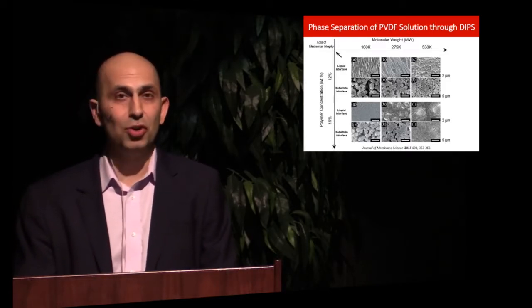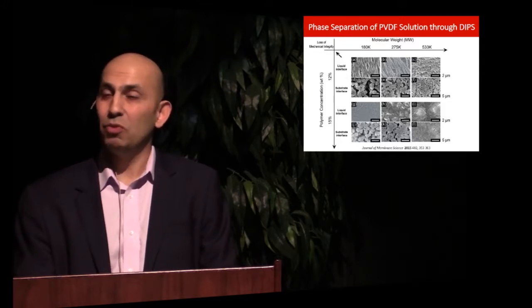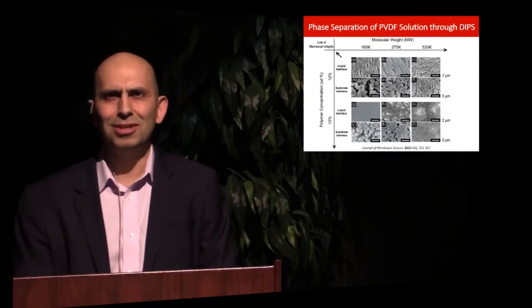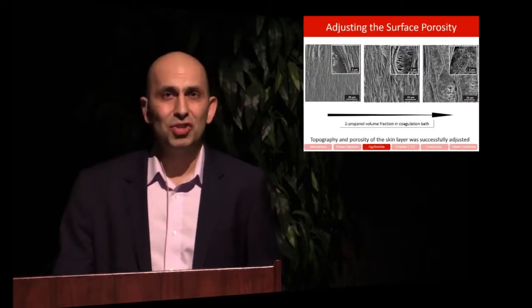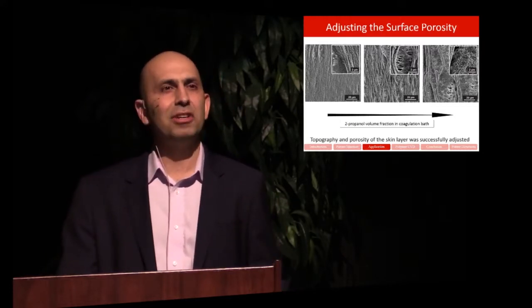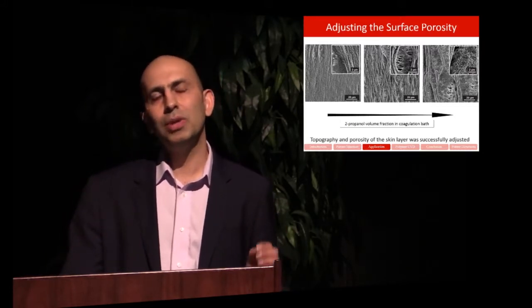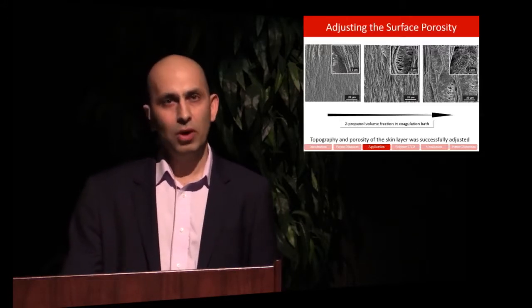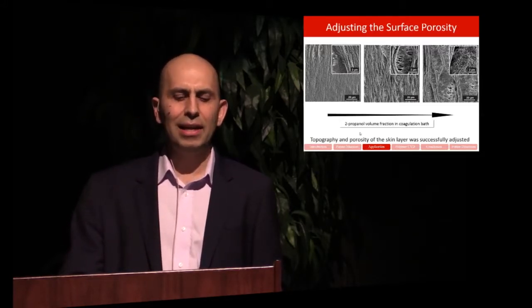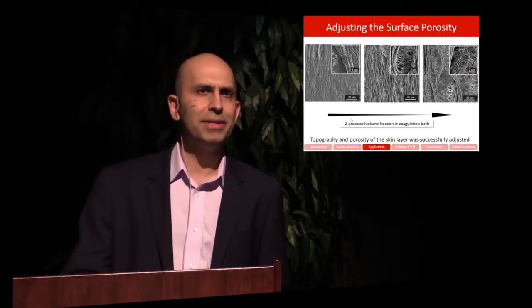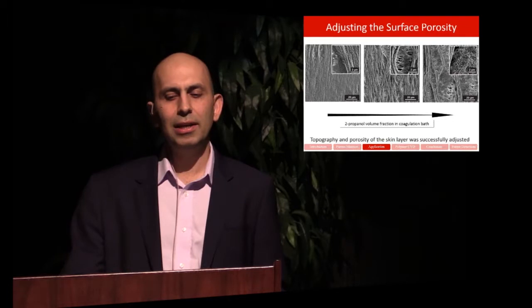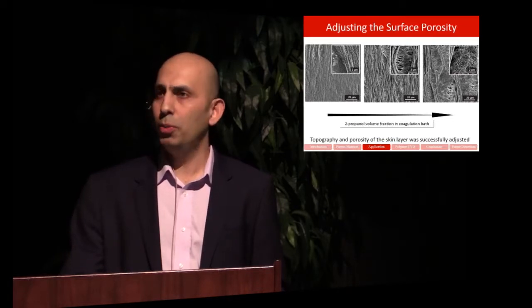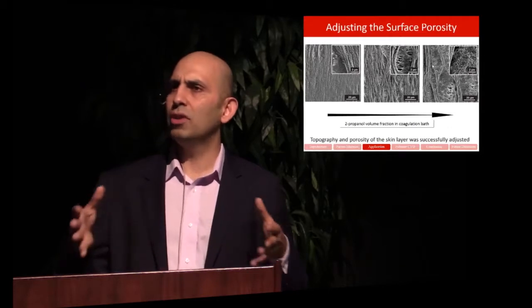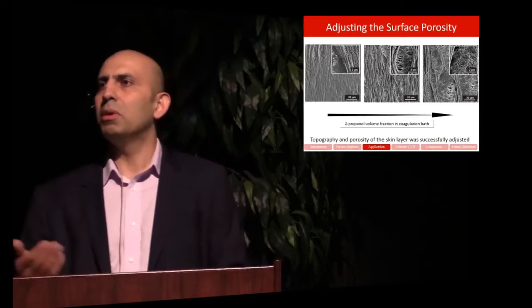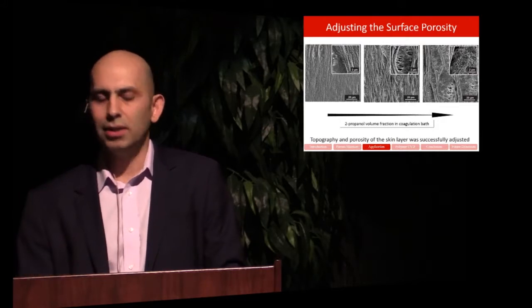So we made the materials. It was hydrophobic. It was porous, but the top surface was closed. So there's no way for vapor to go through. So the next step was how to open this structure. So we again went after the processing condition. We started adding something to that third component, that non-solvent, which we call the coagulation bath. In this case, we started adding a little bit of 2-propanol, less than 10% volume. And we started seeing that as we increase the amount of the propanol in that coagulation bath, the structure of the top surface is opening up. So we can create membranes with the desired surface porosity.